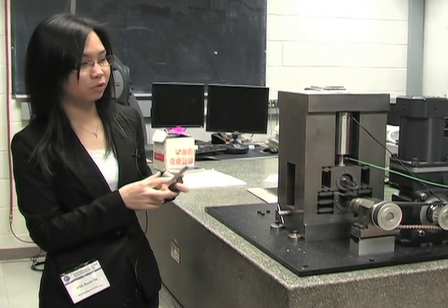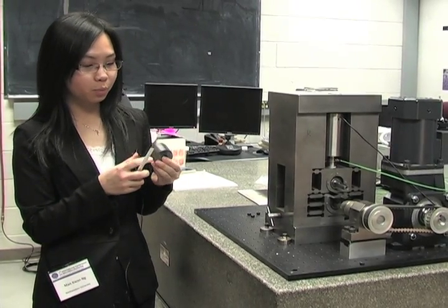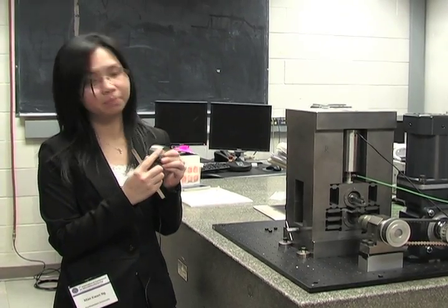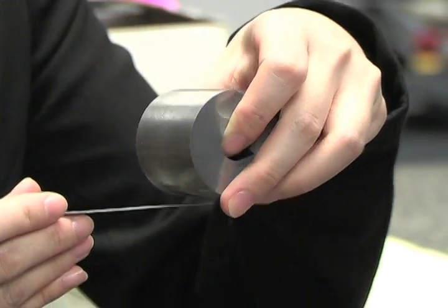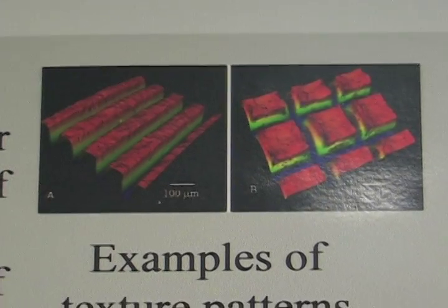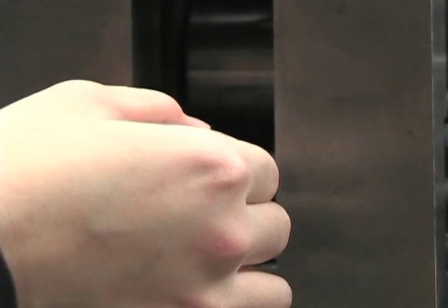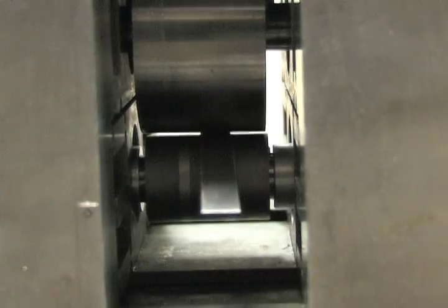I'm doing some research about the surface texturing. Here is the micro rolling mill. And doing the texturing we have a roller. This roller have some pre-textured fixtures on it when it's rolled and the material is printed with some channel on it and this is the working principle of this rolling mill. During the rolling process the material is passing through the roll gaps when it's rolled the friction force will draw the material between the roll gap and the channel is printed on this material surface.